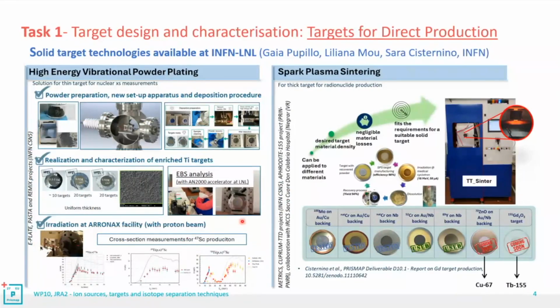I would like to start with targets for direct production. In particular, I would like to illustrate the work done by my colleagues at INFN. They use the high energy vibrational powder plating technique to produce thin enriched titanium targets for the cross-section measurements. The irradiation tests for these targets were done at ARRONAX, and they were capable to measure the cross-section of scandium 47. They also work with the spark plasma sintering technology for the production of the targets.